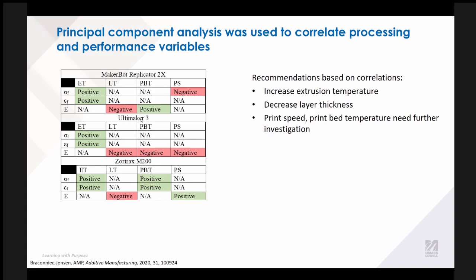We have some conflicting results for the print bed temperature, and similarly we have a little bit of conflicting information about our print speed. And so in general, the recommendations would be to increase the extrusion temperature as much as reasonable and decrease your layer thickness.